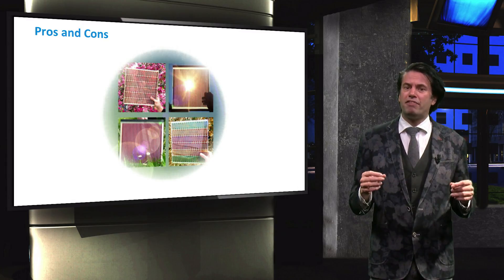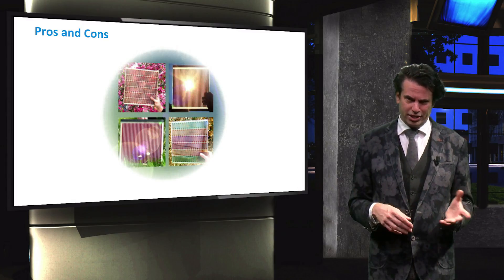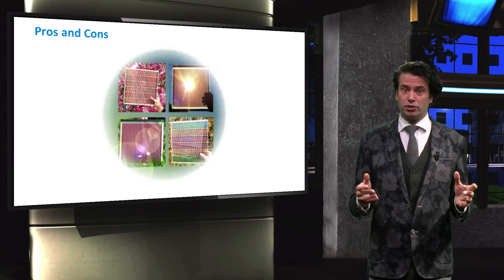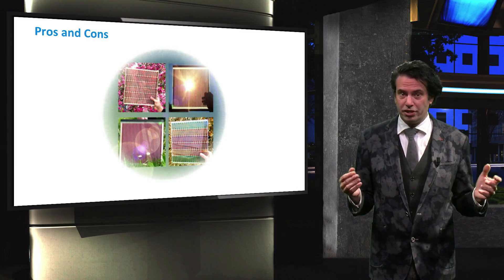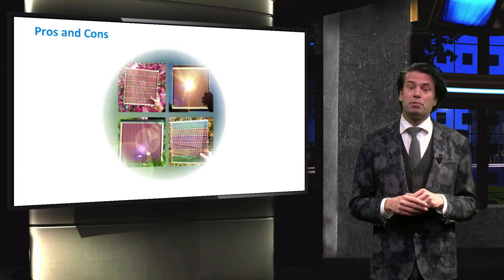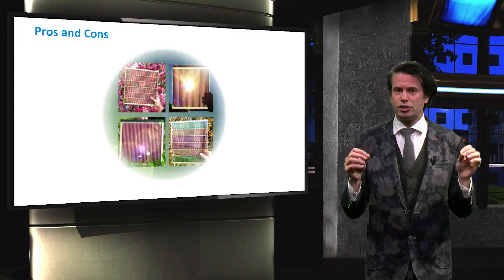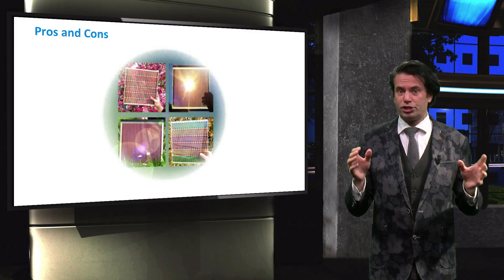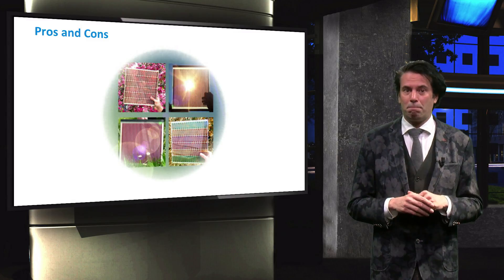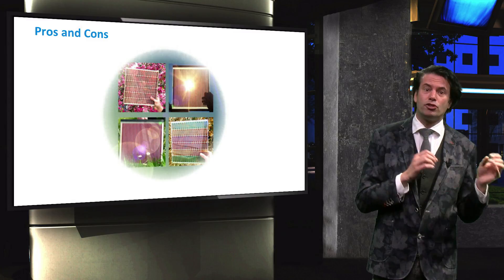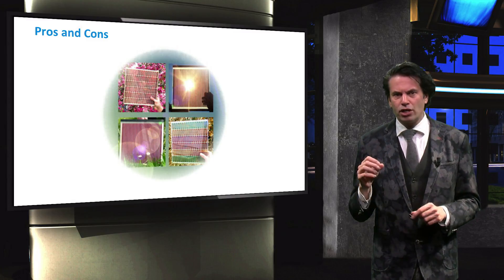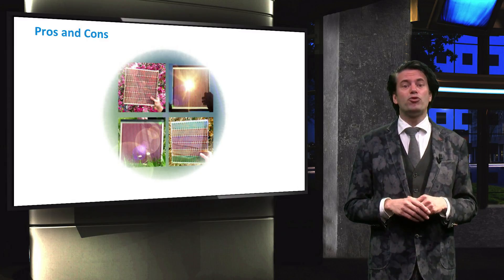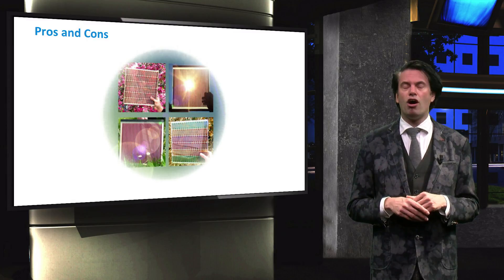The advantages of dye-sensitized PV devices include the low cost of producing the device. A disadvantage is the stability of the electrolyte under various weather conditions: at low temperatures the electrolyte can freeze, stopping power production and potentially causing physical damage to the cell. Higher temperatures result in thermal expansion of the electrolyte, making encapsulation of the modules more complicated. The technology also faces challenges such as replacing the expensive platinum electrode with cheaper materials, developing more stable and resistive electrolyte materials, and improving dye sensitizers to enhance spectral and bandgap utilization of the solar cells.